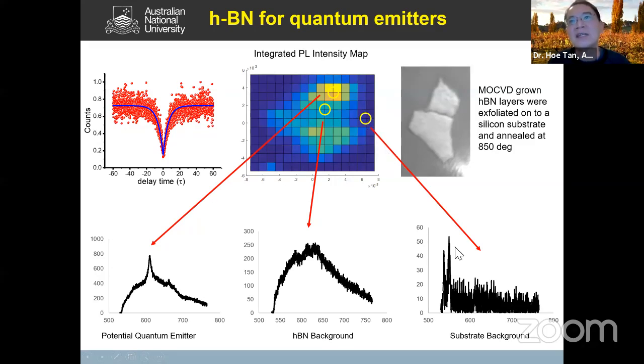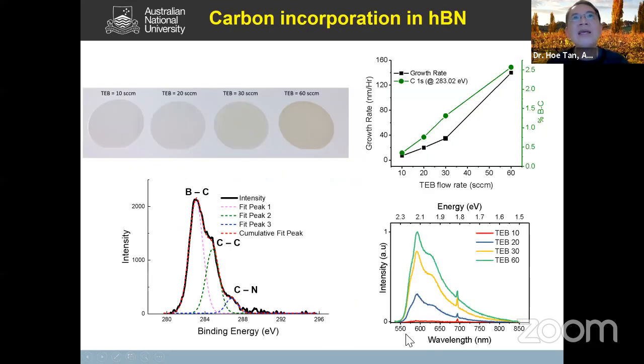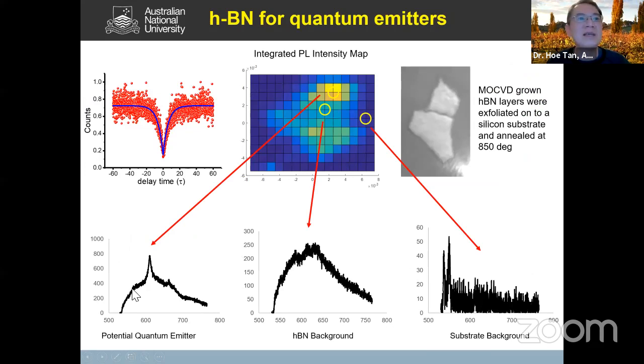So obviously outside the HBN, you have no emission. In some regions here, you can see just a very broad emission peak. But in some of the very bright spots, in addition to this very broad peak, you see this very sharp emission. So these are the quantum emission, or the single photon emission.